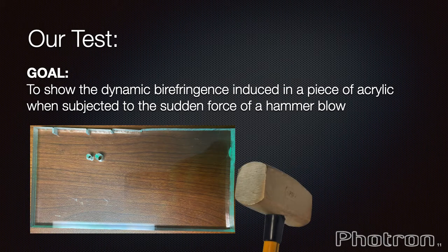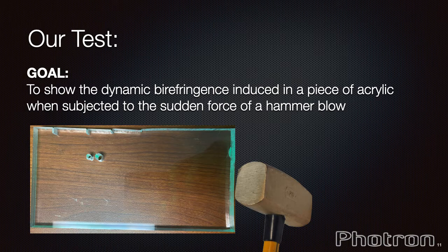For our simple test, we took a 190mm tall by 95mm by 10mm thick piece of acrylic, with a couple of holes and several cuts in it just to show residual stress patterns as well as induce some interesting astigmatism. This was then struck with a hammer at the top right-hand side of the image.